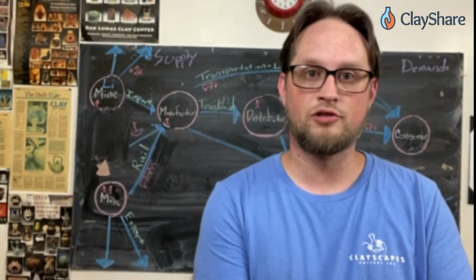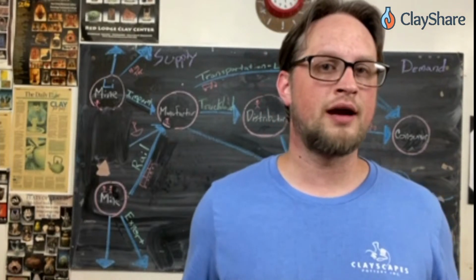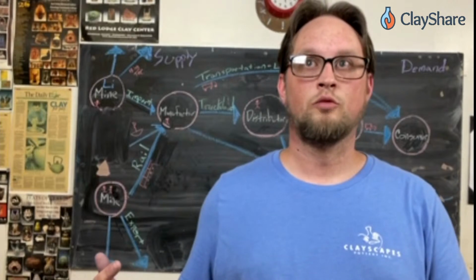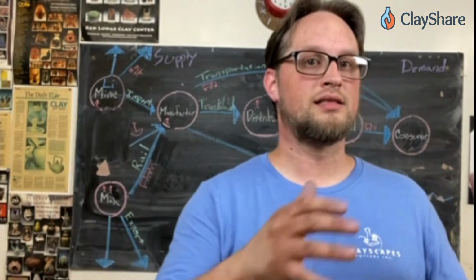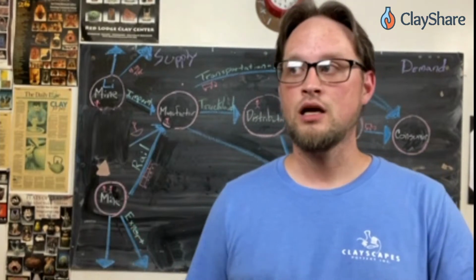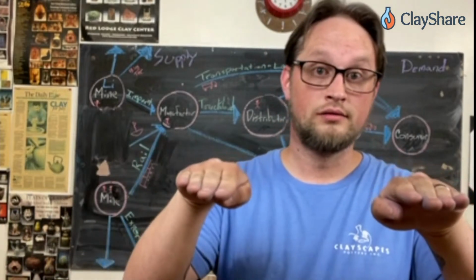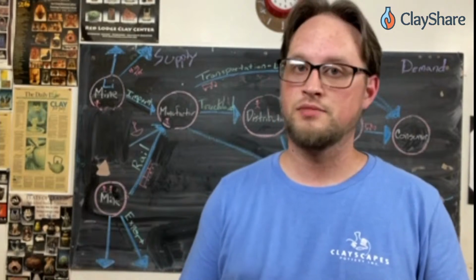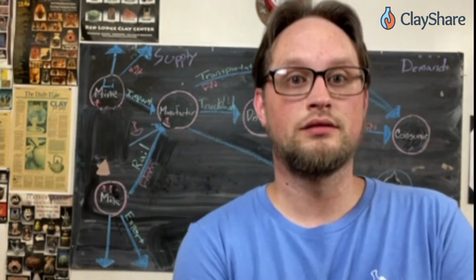I'm not saying it's going to be bad, totally. If you've got a glaze recipe that calls for iron oxide, put it in there. Do a 100-gram test. If you like it, use it. Just know that once that iron's gone, you can't make it anymore. You would have to do more testing with current iron and see what it looks like. I suppose you could make a 100-gram batch of a white glaze and make another one. In one 100-gram batch, you put the old iron in, and in the other, you put the new iron in, same amount, and fire them next to each other in the kiln. That is going to be your best way to figure that out.